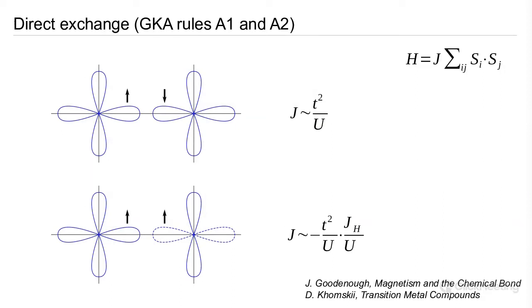In the same scenario, but if we had an unoccupied orbital, which is represented by this dashed line at the bottom here, then what happens is essentially that the single electron that's singly occupied on the left just hops over virtually, spends a bit of time in that orbital, Hund's couples to the rest of the unpaired spins on that atom, and then hops back again. So this gives rise to an effective ferromagnetic exchange interaction. So we have now minus t squared on U, but it scales with this Hund's coupling local to the ion.